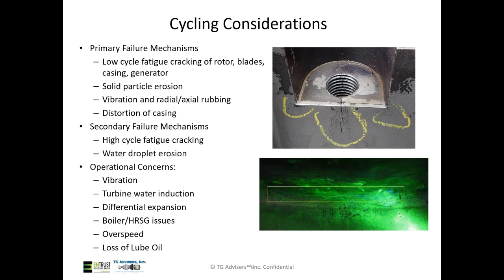We can see issues during startups with vibration. We're going to pass through critical speeds of the shaft where we see increased deflection. We also have something called differential expansion, where the rotor and the casing are heating up at different rates. And there's potential, if we don't have sufficient clearances in the unit, that stuff can touch that's not supposed to, leading to damage or more vibration. We can also see casing distortion. Some of the secondary failure mechanisms: high cycle fatigue, that's vibration-based cracking. We'll hit on that a little bit later. Water droplet erosion. Typically when we're starting up a steam turbine, the conditions of the steam are not great. So we can get quite a bit of moisture and also a little bit of erosion damage from that.